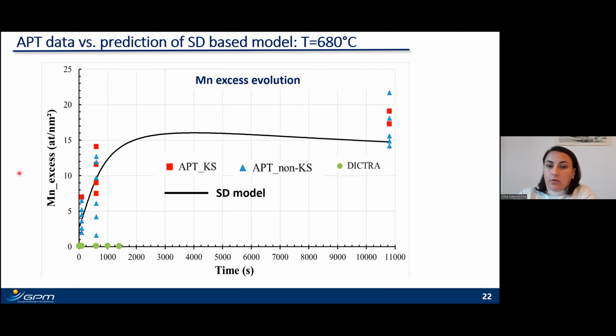So first of all, from this graph, we see the tendency of manganese excess to increase with time, which is clearly observed experimentally and also predicted by the solute drag model. And of course, we must take into account a significant scatter in the experimental data. For the moment, it is a bit difficult to define appropriate parameters for a solute drag model in order to provide an accurate quantitative description of the austenite to ferrite phase transformation.